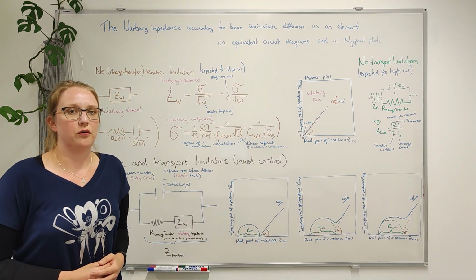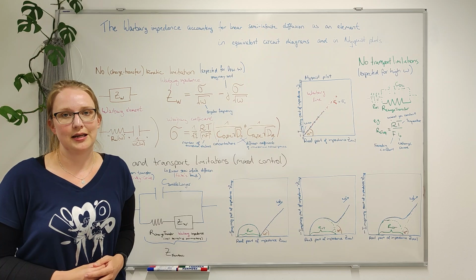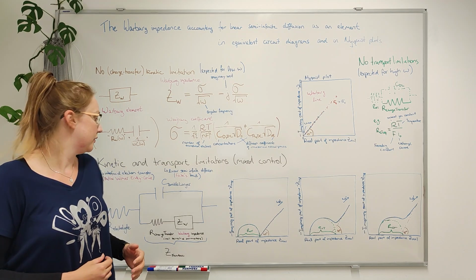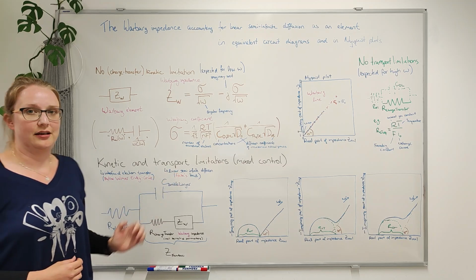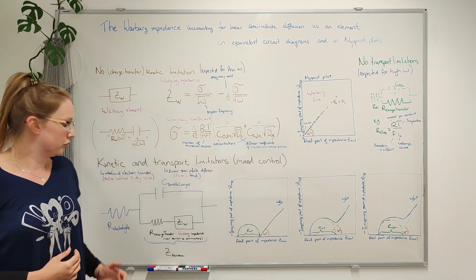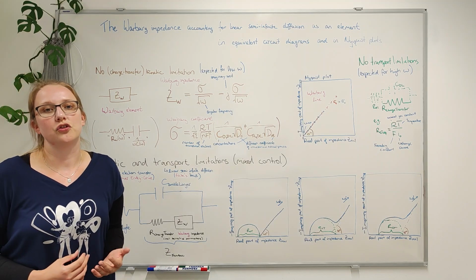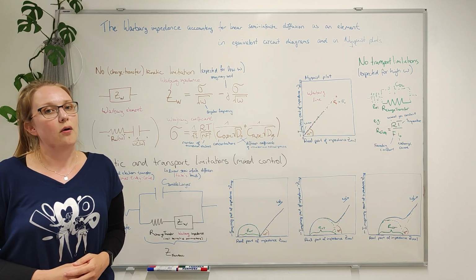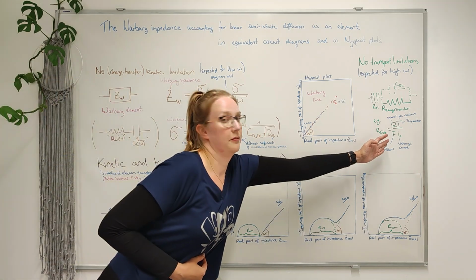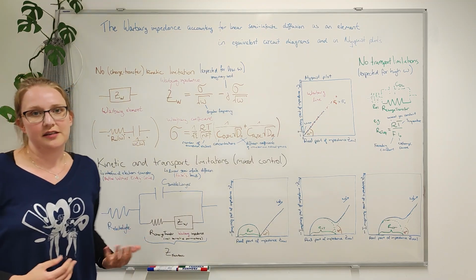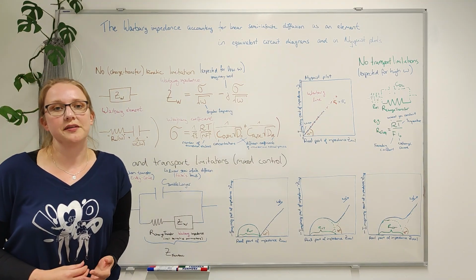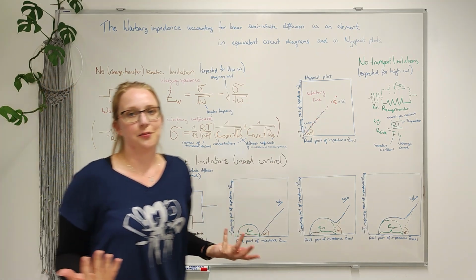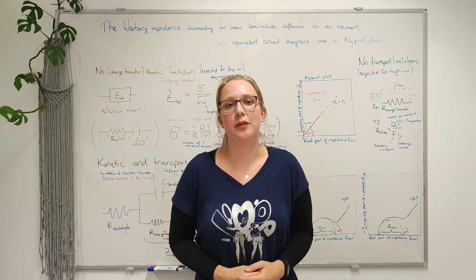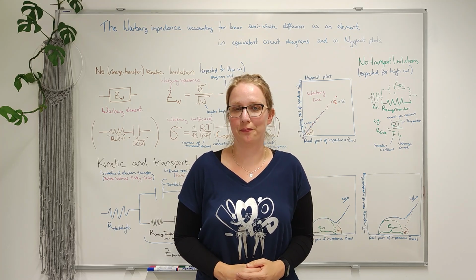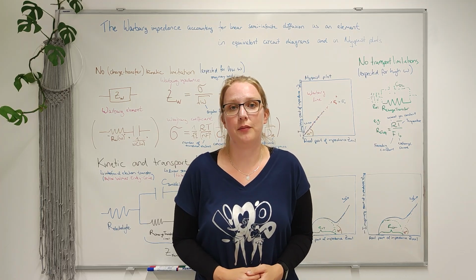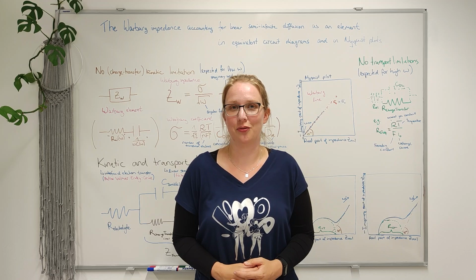Remember that we derived an expression for the Warburg impedance which still contained kinetic parameters like heterogeneous rate constants when we considered interfacial electron transfer and linear semi-infinite diffusion. This description of a Faradaic impedance comprises different terms for ZW and RCT than our previous approximation in Basics of EIS. It thus offers a broader application and can account for mixed kinetic and transport control. As we have seen in Kathleen's experiment, changing the concentration of the redox couple can affect several features of the impedance spectrum. Today, we will see what happens if we affect the mass transport by rotating the disk we use as working electrode.